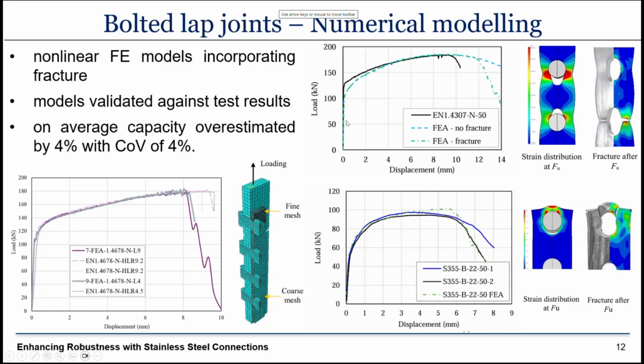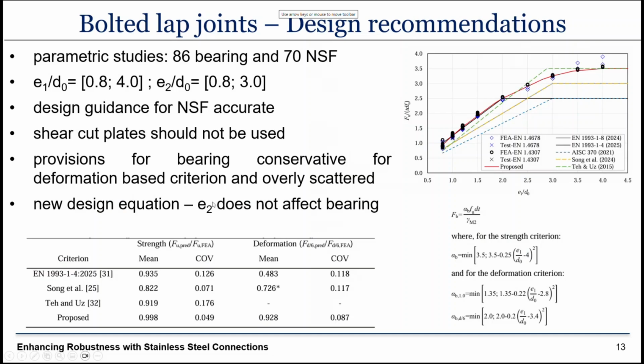Here we can see the experimental and the numerical curves for net section fracture, for bearing failure, and also under high strain rates. Overall, the agreement is not bad, which allowed us to proceed to parametric studies. So upon validating the model, we ran a total of 86 models in parametric studies for specimens failing in bearing, and 70 for specimens failing by net section fracture, both under static loads.